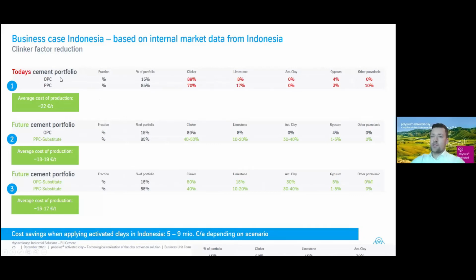So this is today's cement portfolio. And then we built up two scenarios. So the second scenario is to substitute the PPC by a PPC substitute, which is then activated clay cement. So here we can use very low clinker content of around 40 to 50%. We can apply limestone content between 10 and 20%. And we can implement activated clay of around 30 to 40%. So just to give you a number here. And with this composition, you will come up with a quite good quality.